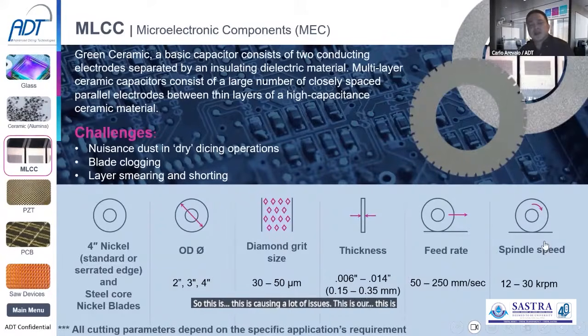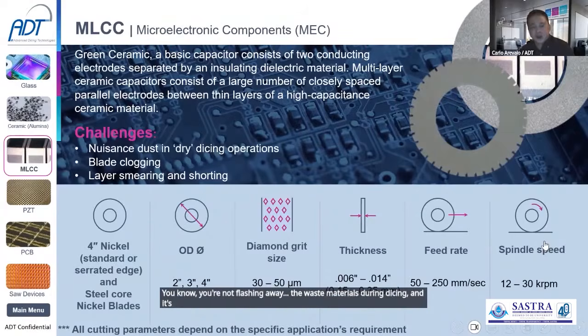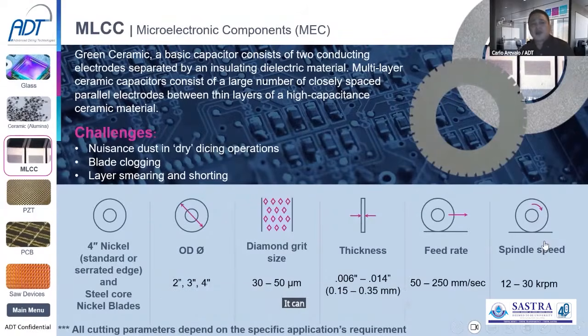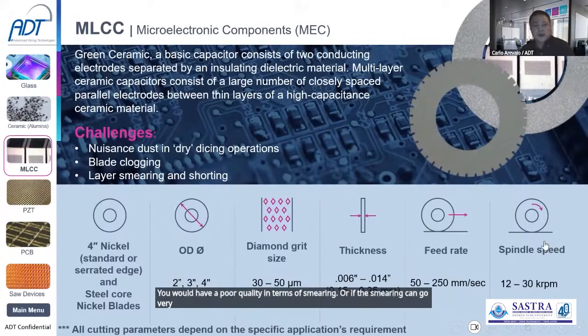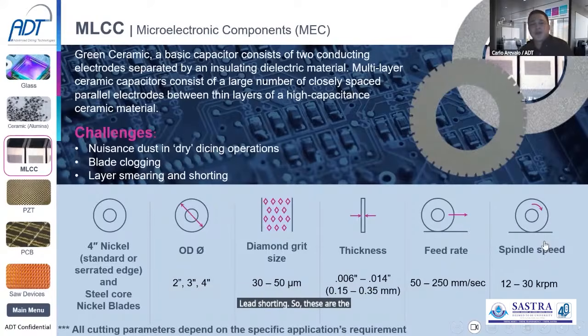This is one of the challenges if you're going to deal with this kind of packaging. Blade clogging is also common because you're not flushing away the waste materials during dicing, and it's going to load up on the blade. It can clog your blade, and it can load up your blade. So when you have a loaded or clogged blade, you would have poor quality in terms of smearing, or the smearing can go much worse, and it can also lead to lead shorting. So these are the few challenges that need to be looked at.